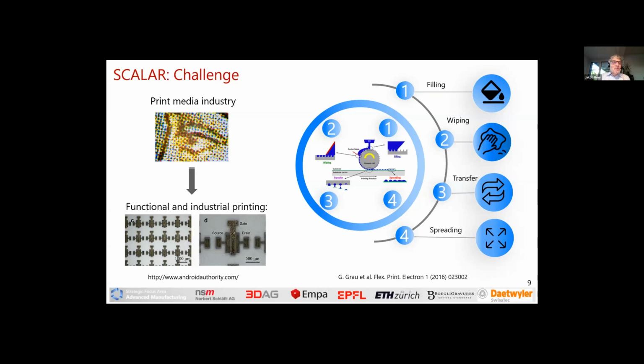Anyway, to really make gravure printing fit, you need to first of all understand the process. Gravure printing sounds fairly easy. You engrave a cylinder and fill the cylinder with ink, and this ink is then transferred to a substrate. But indeed, it's a more complicated process, and it involves 4 major steps. One is filling the cavities in your gravure cylinder. Second step is wiping the excess ink off. The third one is the ink transfer or ink splitting process. And the fourth one is spreading of the ink on the substrate, and that will form your final figure.